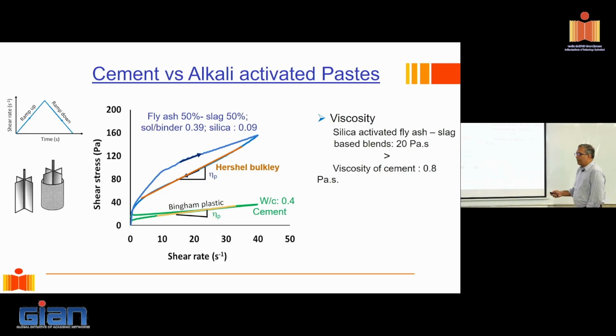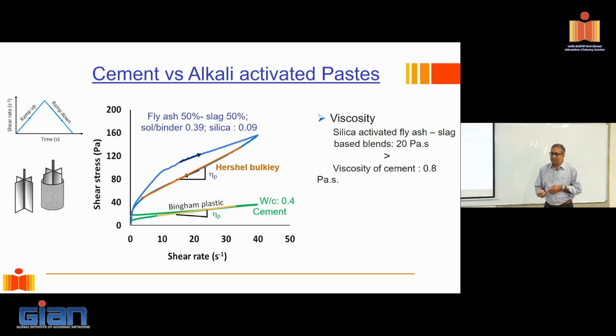Now look at the difference in the plastic viscosity. Typically my alkali activated materials will be much more viscous. That's something I have to prepare for. What are the consequences of this? If I am to pump this material, what does the pumping pressure depend upon? The viscosity. So expect that this material will physically be stickier. It's going to be much tougher to pump. Your pumping pressures will go up. If you induce flow, it doesn't want to flow. The reason is it has a very high plastic viscosity. This is something that we have to contend with.